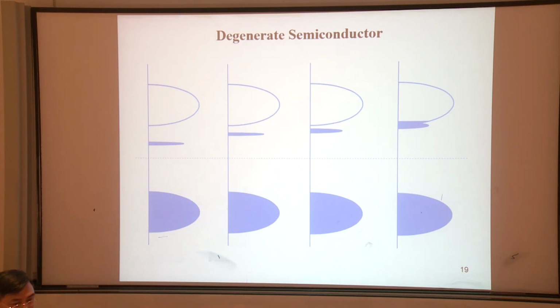So this is a very important material. Usually we have ceramics that are non-conducting. However, if we dope a large amount of dopants, it becomes conducting. And it's still transparent. Usually metal is not transparent. But nowadays we want to make something that's transparent while it's conducting. For example, our solar cell: we want the light to be transparent to the solar cell, so it can shine on the p-n junction. However, we want it to be conductive, so electrons can be conducted out. So this is the way that we make transparent conducting materials.